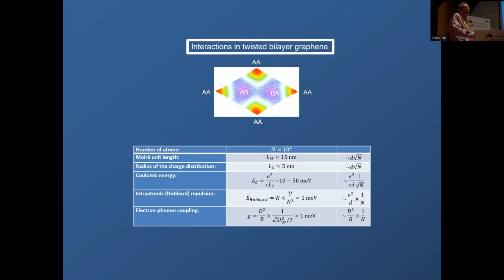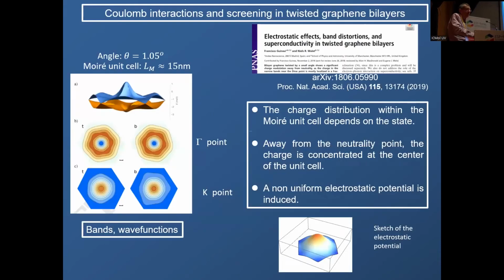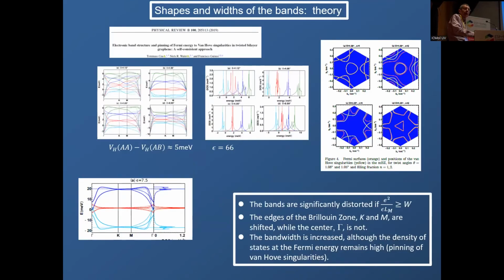And then that creates an electrostatic potential. So as soon as you move away from neutrality, as soon as you change the number of carriers in these systems, you create a non-negligible electrostatic potential, which is not uniform. And what is interesting is that this potential, which is discussed here, in turn changes a lot the narrow bands. So the idea is you change the number of electrons, you create potentials which you do not create in other more conventional 2D systems, and the bands are very narrow, and because of that they're very fragile. So these potentials change them completely.